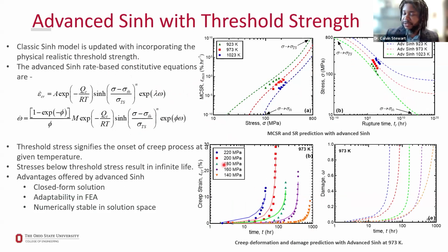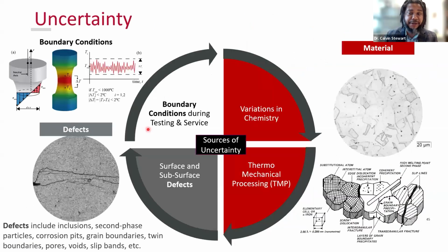Another new model that we've developed and we'll be presenting at Turbo Expo this summer is a threshold-based model. Often in creep flow, there's a question of at what stress levels do you have an infinite life? In fatigue, we have the endurance limit. We know it. We can test for it with a rotating bending machine. But in creep, we can never reach the endurance limit. Infinite creep could be 1,000 years of testing, literal 1,000 years of testing. So we've developed this threshold-based model that helps us to pin down a more physically realistic estimate of what that threshold stress should be, right, compared to other models.